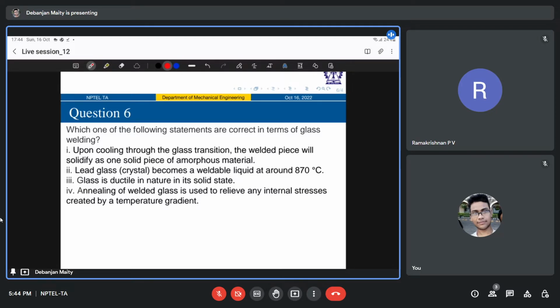And so welding can usually take place by simply pressing these two melted surfaces together, and the two liquids will generally mix and join at first contact. Upon cooling through this glass transition, the welded piece will solidify as one solid piece of amorphous material. Basically, how we do heating is we can use some kind of gas torch or furnace, because the temperatures for melting glass are often quite high. These temperatures may vary depending on the type of glass also. Lead glass becomes a weldable liquid at around 870 degrees C. There is quartz glass, which is fused silica, that must be heated over 1650 degrees C.